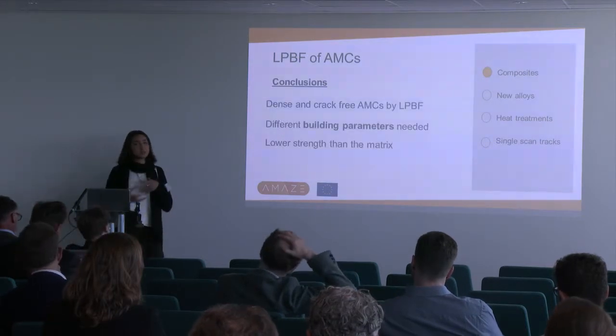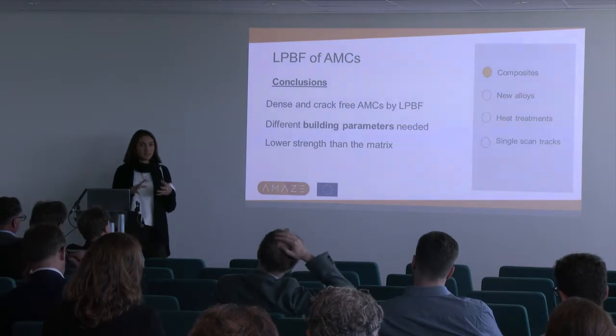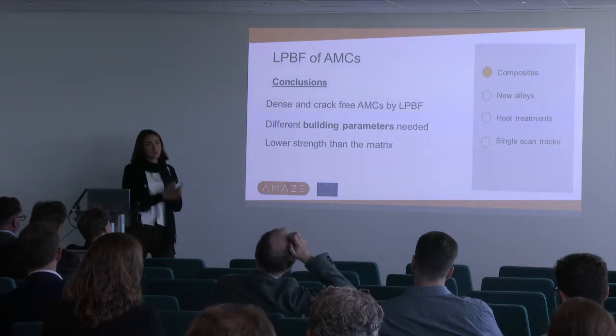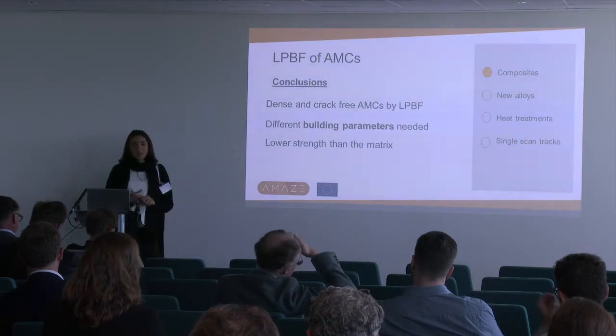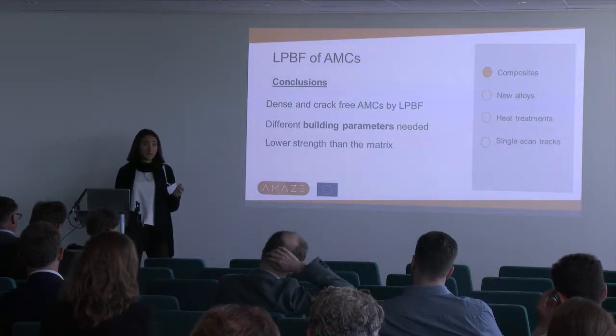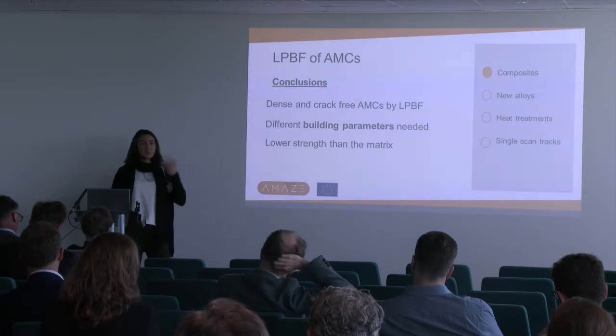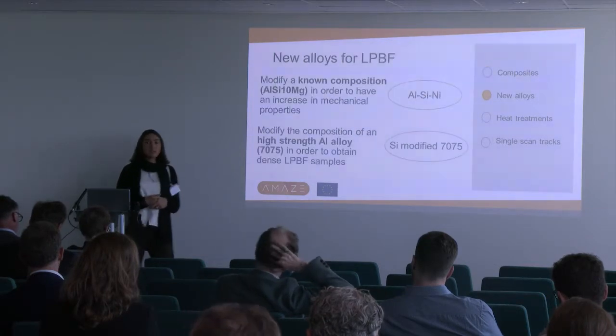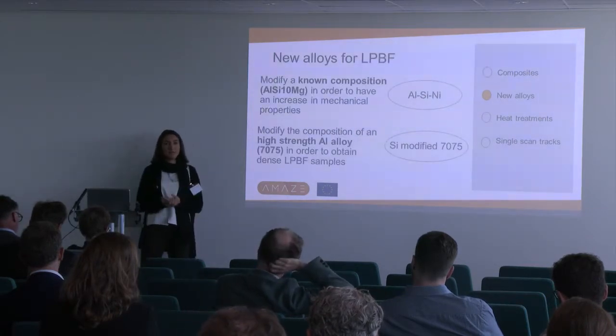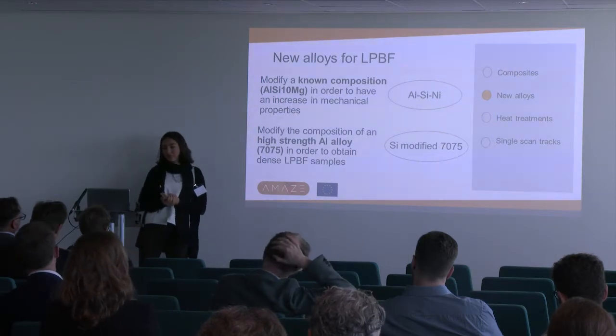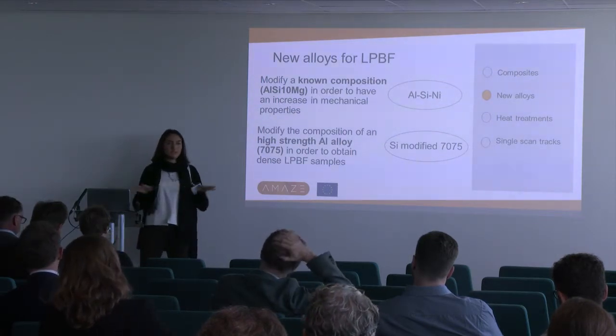So finally, it is possible to produce dense and crack-free composite by selecting the good building parameter. However, these composites have lower strength with respect to the matrix. So we moved to alloy. So how to design an alloy composition for additive manufacturing? So we chose mainly two ways.